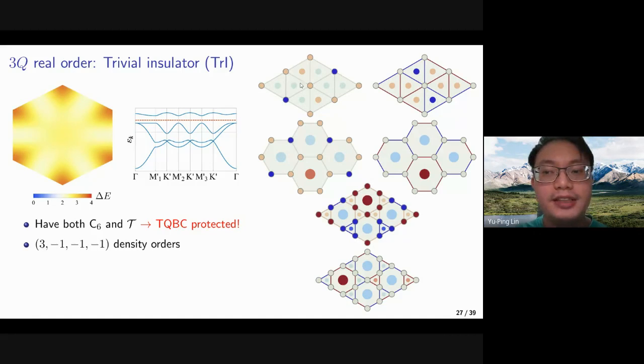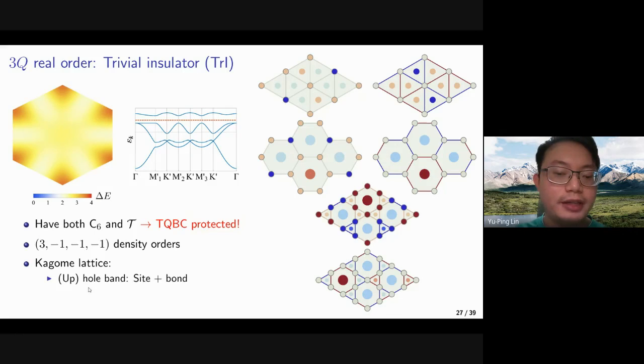Meanwhile, if we look at the density orders, we will have the 3, -1, -1, -1 orders, where we can also see it if we look at the triangle density, which is calculated by summing the site and bond densities around it. The particular thing to notice is that the hole and particle bands have different patterns because the sublattice structures are different. If we look at the hole band, we have the site plus bond orders. And if we look at the particle band, we only have the bond orders.